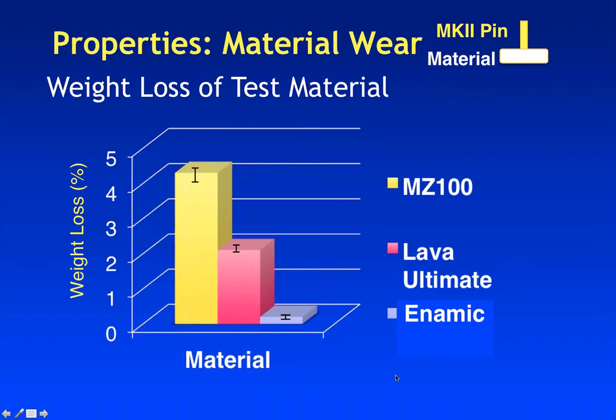If we look at the material weight loss, we have a similar situation where the MZ100 was the worst, followed by Lava Ultimate, and then Enamic, a very small amount of weight loss, significantly better than either of the two materials that we were looking at. So again, it behaves much like a ceramic with respect to wear resistance.